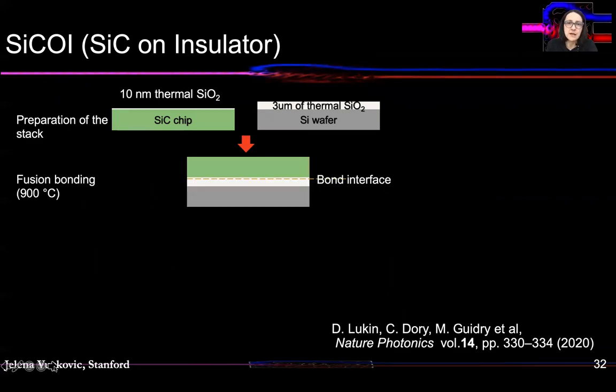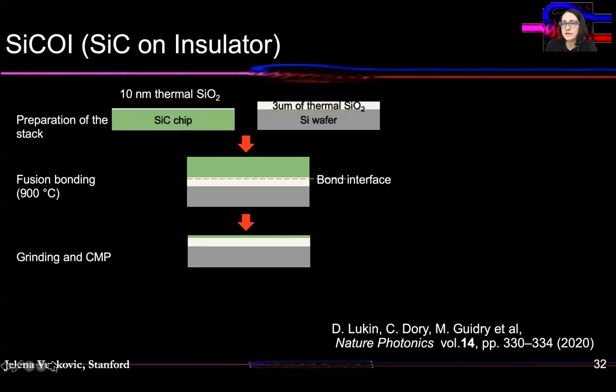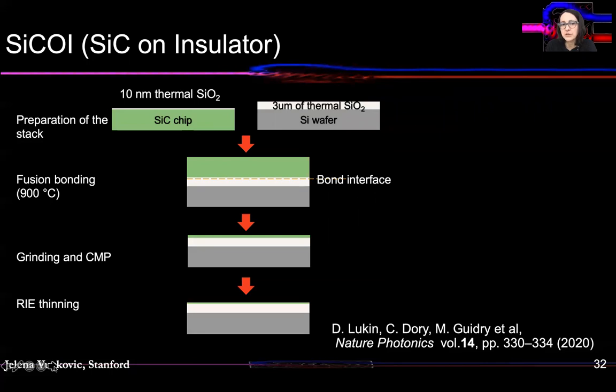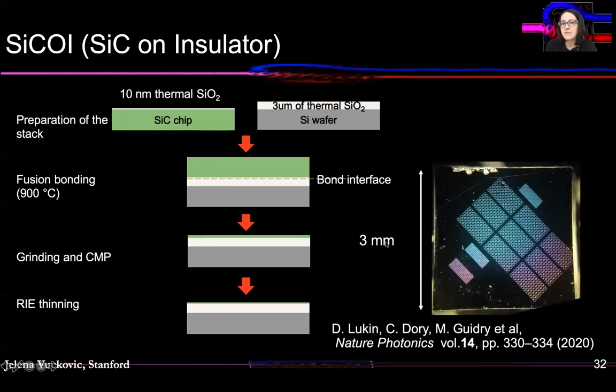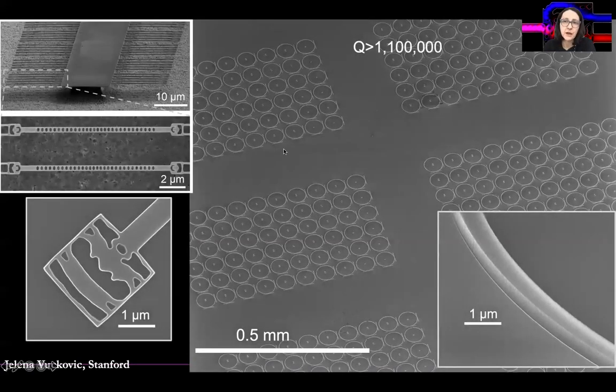We do this by basically bonding and grinding, thinning silicon carbide bonded on oxidized silicon. And we can produce few by few millimeters, very high purity films of silicon carbide, which enable extraordinary quality of photonics. This is not really limited by few millimeters. In principle, with different tools, you could actually go to much larger scales. This is what we can do in a university facility. But few by few millimeters is enough to build very, very large photonic circuits, especially optimized circuits that occupy small footprint. We have excellent quality factors exceeding 1.1 million, completely comparable to silicon photonics.